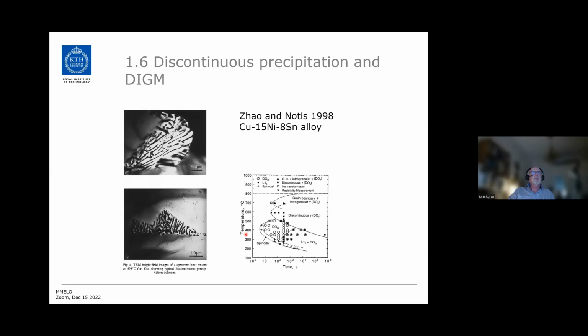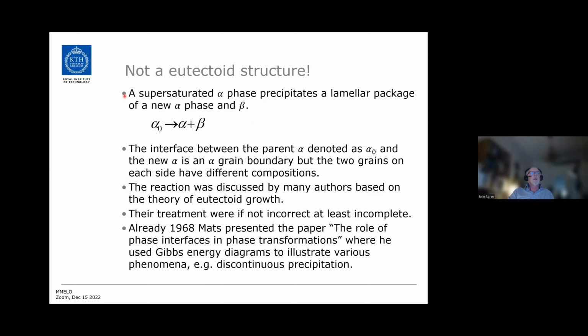Discontinuous precipitation and DIGM. This is a picture from Zhao and Notis from a copper alloy. Well, this is not a eutectic or eutectoid structure. It is only two phases in it. So if you have a supersaturated alpha phase, it precipitates a lamellar package of a new alpha phase, but with a different composition, and a new phase. So the reaction goes like this. This is with the initial composition, and this is with the new composition and the beta phase.